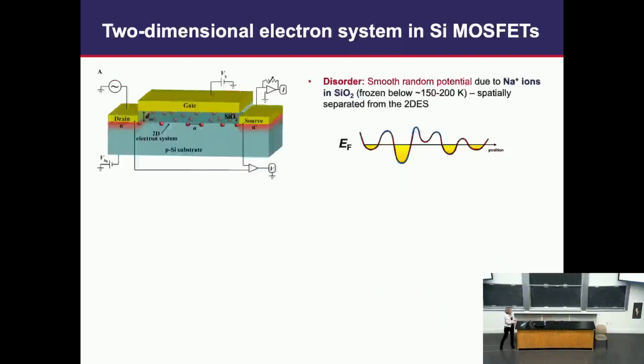Now, these electrons also feel a random potential, due to positively charged sodium ions that are randomly distributed in the oxide, spatially separated from the electrons. They're frozen at the low temperatures of interest. So all we care about is that we have this random potential, a Coulomb interaction, a random potential, and for MBL...